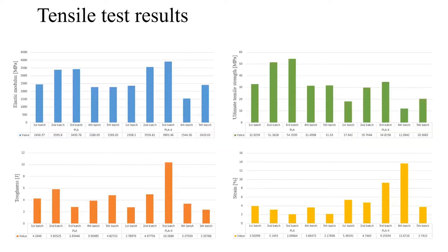So these are the results of one previous paper showing the comparison between PLA and PLA-X. So on each chart you see different mechanical property. From left to right hand side you have PLA and then PLA-X batch properties. What I want to emphasize is that the ultimate tensile strength is greatest in the batches holding highest infill density, so with full infill, with slightly higher values in the circular orientation batch, mostly due to the printing lines being in the direction of the loading, and that's why the forces were a bit higher.